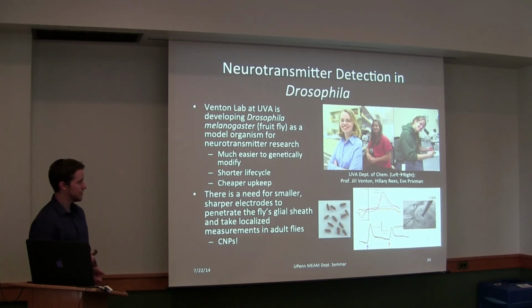So there is a need, in this case, for smaller, sharper electrodes to penetrate the fly's glial sheath. They have this sheath around their brain that's tough to penetrate. Carbon fiber microelectrodes are on the order of a few microns, typically 5 to 10 microns, while the fly brain region of interest is on the order of about 35 microns. So you're looking at a relatively large electrode trying to take these measurements, which they have done. But it would be nice to have smaller, sharper electrodes that can penetrate the glial sheath of these flies, which got us very excited for CNPs.